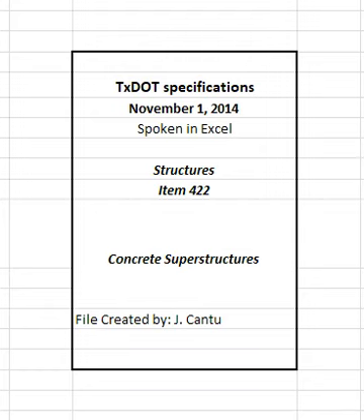Use an approved system of checking to detect any vertical movement of the forms or falsework. Maintain forms for the bottom surface of concrete slabs, girders, and overhangs to the required vertical alignment during concrete placing. Level, strike off, and screed the surface while carrying a slight excess of concrete ahead of the screed to fill all low spots as soon as the concrete has been placed and vibrated in a section wide enough to permit working. Move longitudinal screeds across the concrete with a saw-like motion while their ends rest on headers or templates set true to the roadway grade or on the adjacent finished slab.